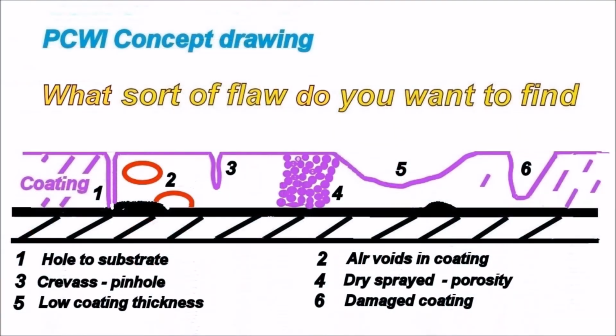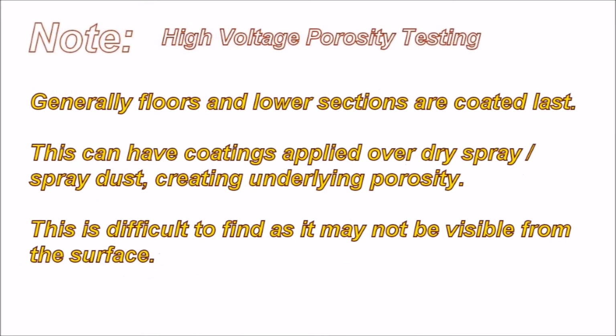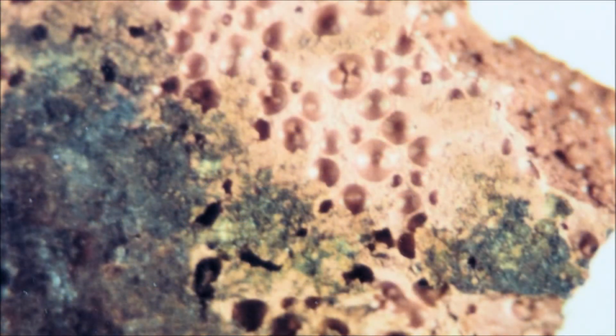Once again, these are the flaws that you would be looking at finding. It's easy to not have enough voltage or to use the wrong probe to skip over those. Generally, floors and lower sections are coated last. This can have coatings applied over dry spray dust, creating underlying porosity. This is difficult to find as it may not be visible from the surface. This is an area of underlying porosity, looking at the back side of the coating. This would be difficult to find. A further section of this showing the first coat, and this is in between two coats actually.